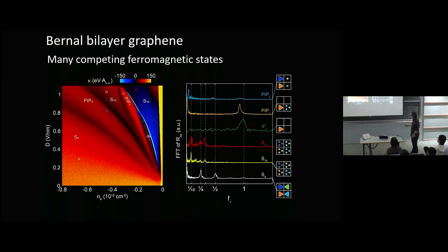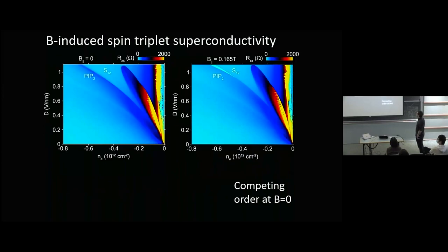But if you look carefully at Bernal bilayer graphene, indeed, it has tons of these same types of Stoner transitions. They're at somewhat lower density and higher electric fields, but basically the physics is quite similar. The details are different. In the process of figuring out why Bernal bilayer graphene didn't superconduct, because of course it doesn't superconduct, we found that it does superconduct, but it superconducts under very strange circumstances.